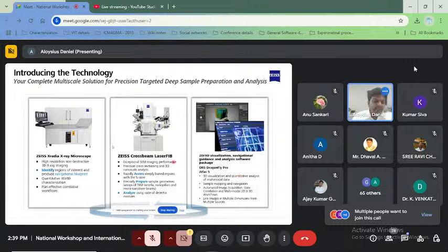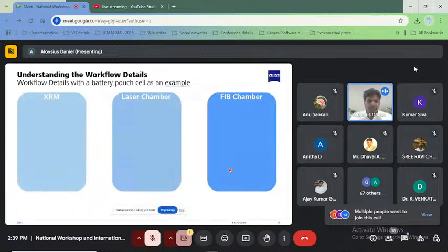So this complete workflow is controlled by tested and proven software platforms, which ensures that when you move the sample from one technique to the other technique, there is complete coordination between this movement of the sample with respect to the region of interest that has been identified, and you do not compromise on the data that you collect from the actual region of interest. So that's what we do.